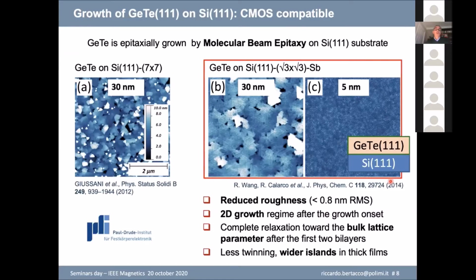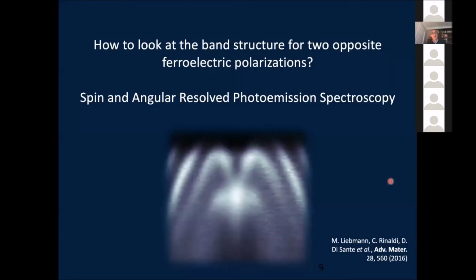So we found people from PDI, a group of Raffaella Calarco, who were really very good in producing nice films by MBE on silicon 111 substrates. And okay, it's not so easy to grow germanium telluride, but the quality was enough to study the peculiarity of bands, also with reference to, I'll say, angle-resolved photoemission experiments. And this is one of our first images of the bands obtained in collaboration with a group in Berlin. And it was a measurement carried out at BESSY.